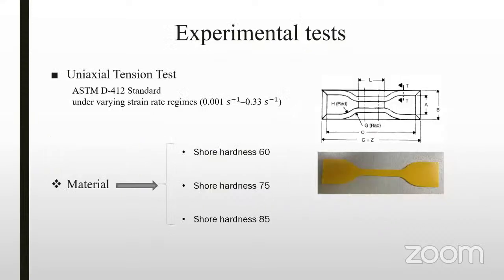As I discussed, to calculate the 9 coefficients of the Mooney-Rivlin model and the coefficients of the dynamic increase factor, I had to do some experimental tests. The tests I have done are the uniaxial tension test based on the ASTM D412 standard. These tests were performed for all 3 shore hardnesses of the polyurethane under varying strain rates from 0.001 per second to 0.33 per second.